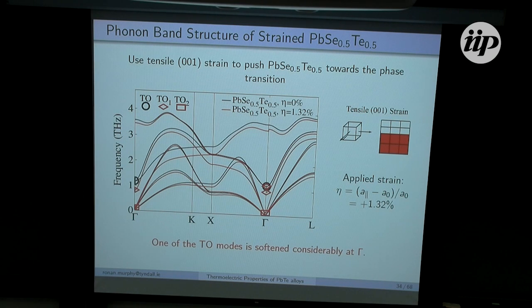So I have here the phonon band structures of this lead telluride, lead selenide alloy unstrained in black and then strained in red. And again, it's a pretty similar story. We see that away from the zone center, there's a little bit of difference in the phonon frequencies, but they're largely similar. But the main difference, again, occurs right at the gamma point, where one of the TO mode frequencies has dropped from about maybe 1.2 terahertz down to about 0.1. And just to mention again, in this case, we've applied 1.32% of strain.